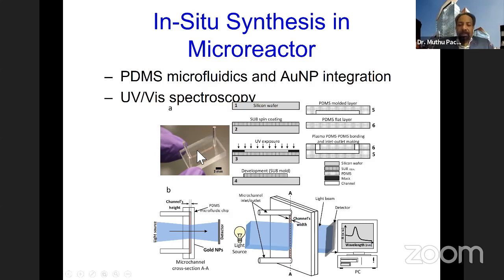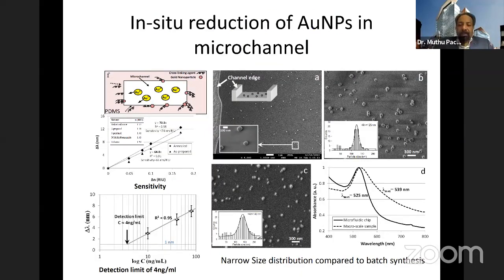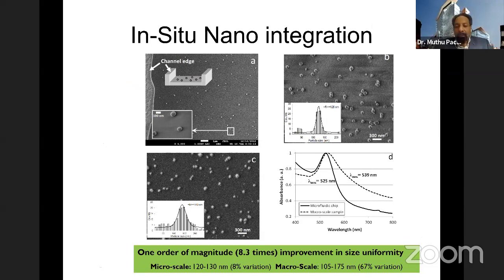You can also see the in situ PDMS nanocomposite here. You can see the red color microfluidic channels in which basically the precursor was allowed to react with the curing agent of the PDMS. So we get this PDMS nanocomposite with the microfluidic channel, which is ideal as a sensing platform. And this platform was used for sensing growth hormones. You can see that we can go up to the detection limit of 4 nanogram per ml. So the LSPR with the gold got us to 4 nanogram per ml inside the microfluidic channels, which is very, very interesting for us.